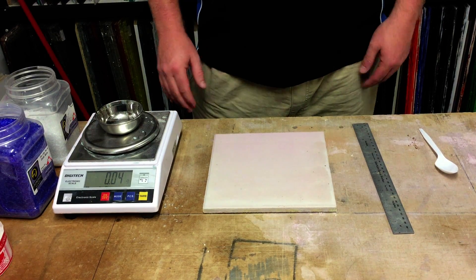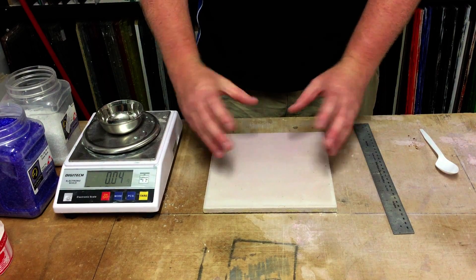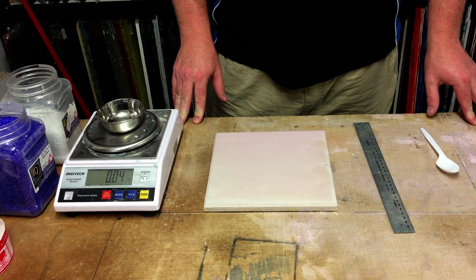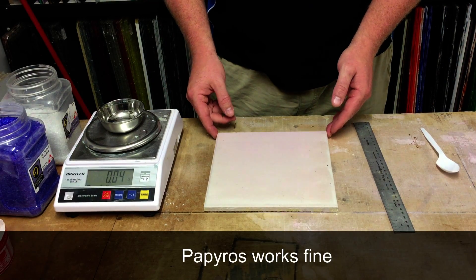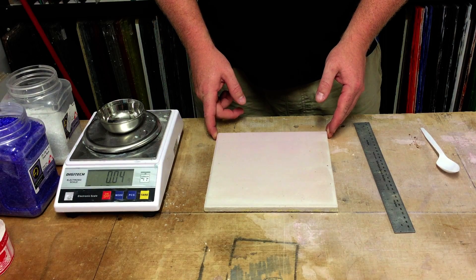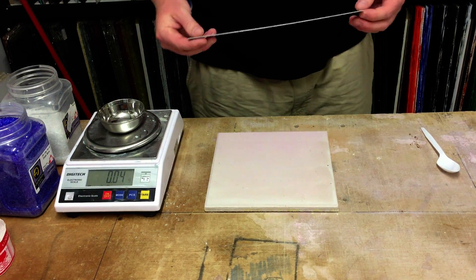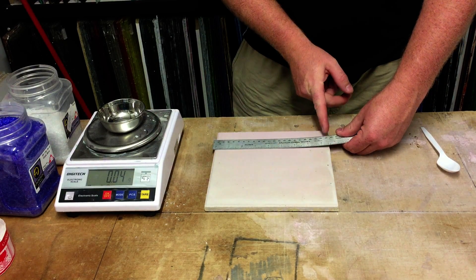We used high fire primer because it forms a harsher finish, and when the frit makes itself into a lace it will drag slightly and potentially pull up a lighter primer. To be honest, we've never tried Primo or Papyrus — we just use high fire, but it will probably work fine on both of those as well. How much frit do you use? We have a pretty simple rule: 2 grams per square centimeter.